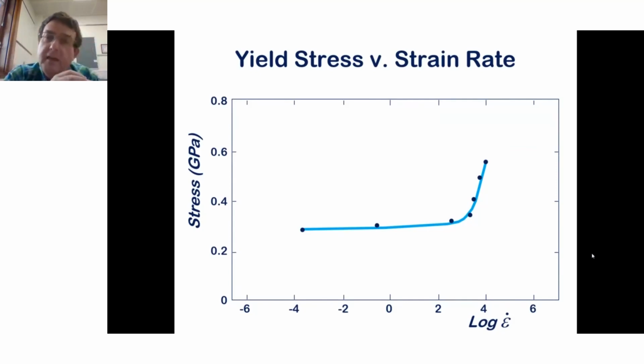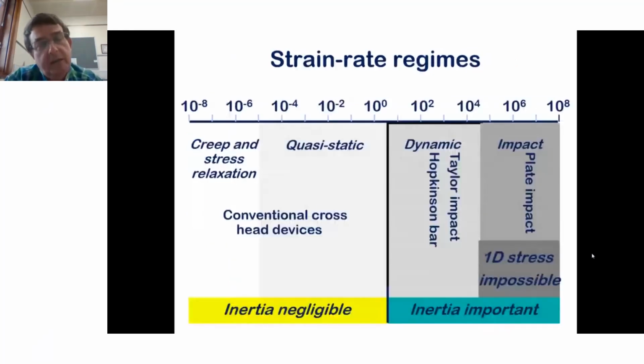This graph indicates that materials will behave differently under those kinds of more extreme loading conditions than they will under quasi-static loading. So this little table here shows you strain rate versus strain rate regime, going from 10 to the -8 to 10 to the +8. And there are versions where people use laser-driven loading, which I won't discuss, but it's definitely out there, definitely well known, where you get strain rates of 10 to the 10.